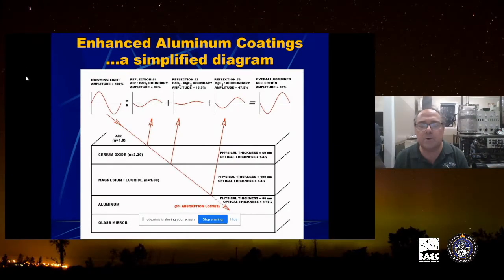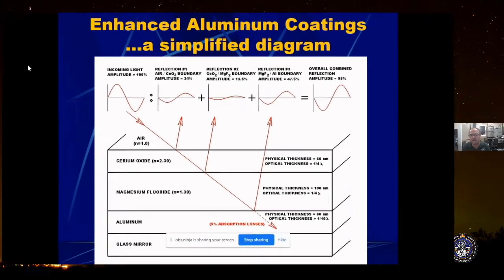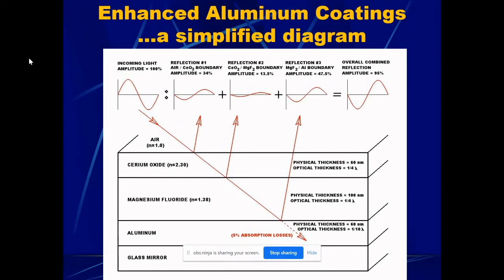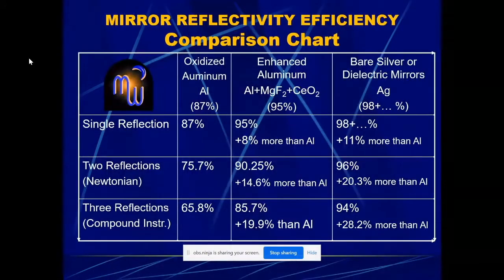The whole thing with the aluminum coating is that it wastes about 5% of the energy, whatever hits it. So in this case, it's only absorbing 5% because 50% of the light or so has already been reflected by the dielectric coatings. Now this is just a very simple one. You can increase this again by adding another pair of cerium dioxide and magnesium fluoride, and that way you can get up to 99% as well. But it gets pretty tricky when you do that, and it's very, very hard to do these types of coatings on large surfaces as well.